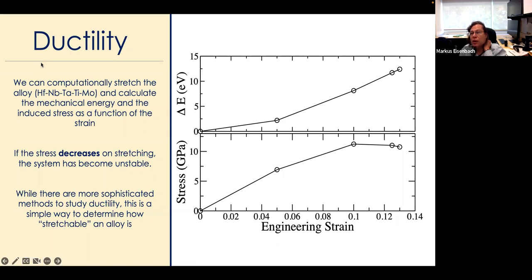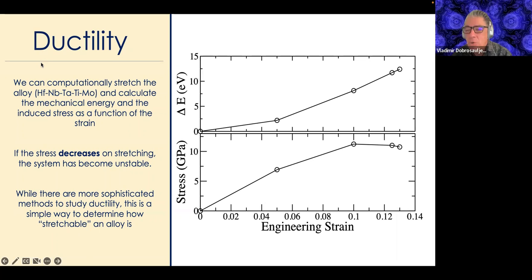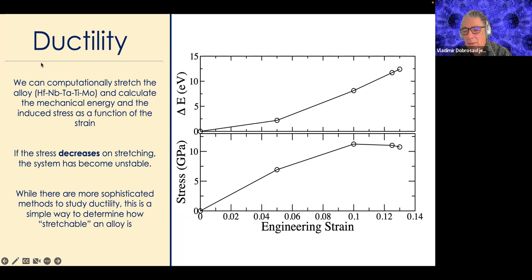Just normal molecular dynamics at temperatures you're usually interested in. But even with a classical force field, it takes a very long time. So Marcus, this is not true. It's not the same in all systems. In simple systems with ordering, like ferromagnets, Monte Carlo can be done very easily. But if you have a somehow glassy ordering and a lot of frustration, then even Monte Carlo methods can be very difficult to do. So it's not always the same.